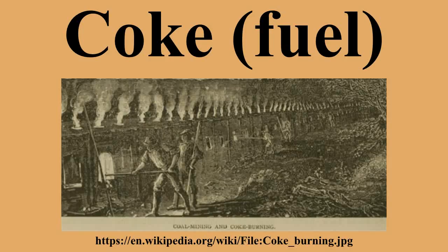Bituminous coal must meet a set of criteria for use as coking coal, determined by particular coal assay techniques. These include moisture content, ash content, sulfur content, volatile content, tar, and plasticity. This blending is targeted at producing a coke of appropriate strength while losing an appropriate amount of mass. Other blending considerations include ensuring the coke doesn't swell too much during production and destroy the coke oven through excessive wall pressures. The greater the volatile matter in coal, the more byproduct can be produced.